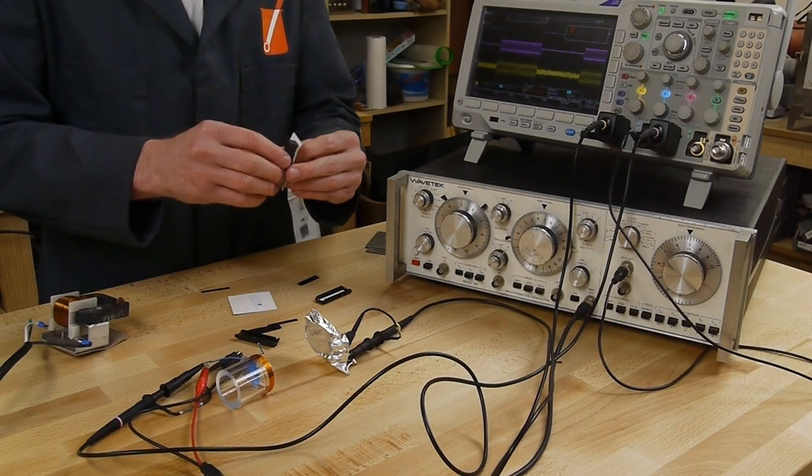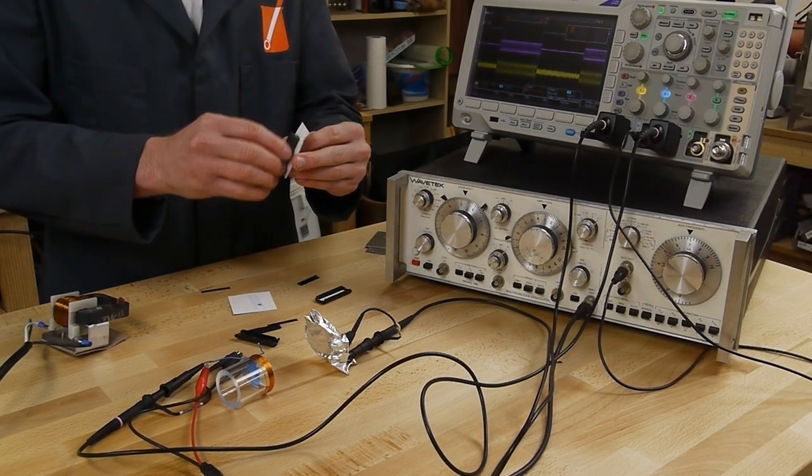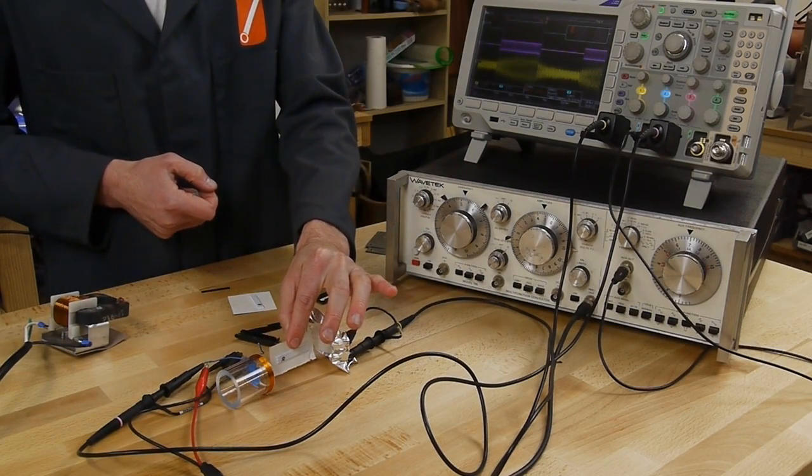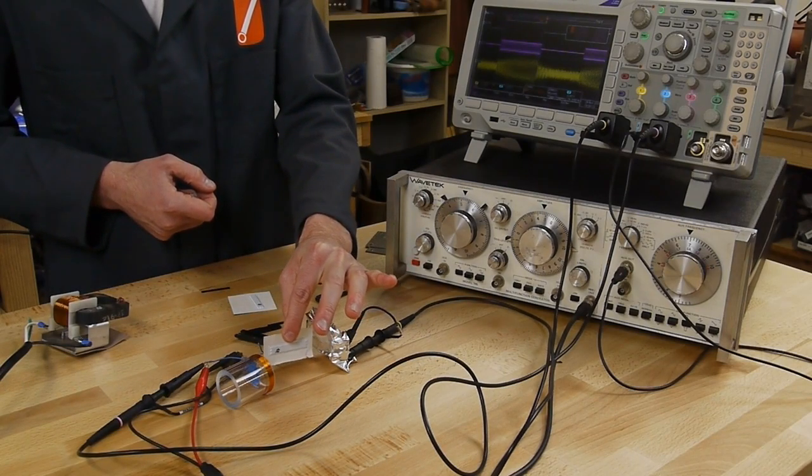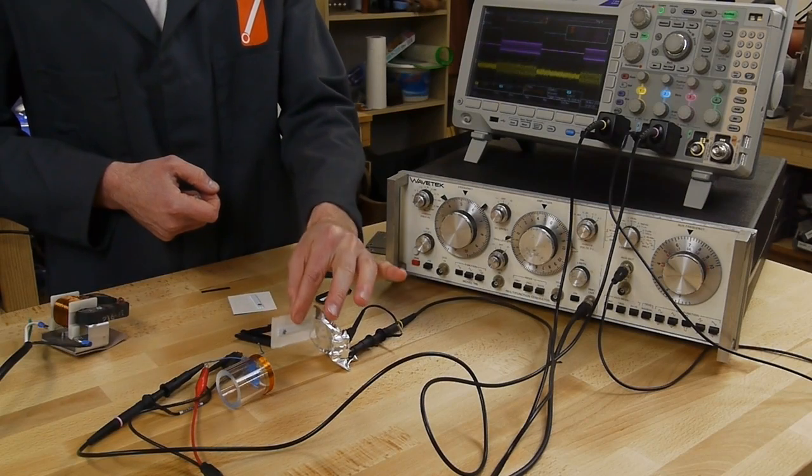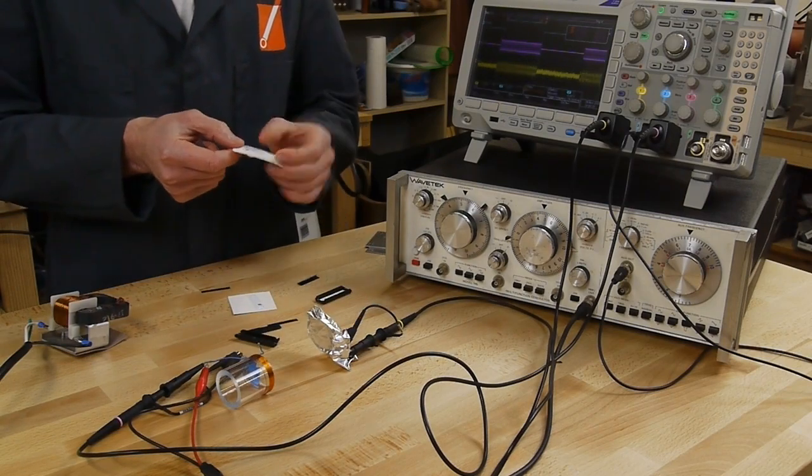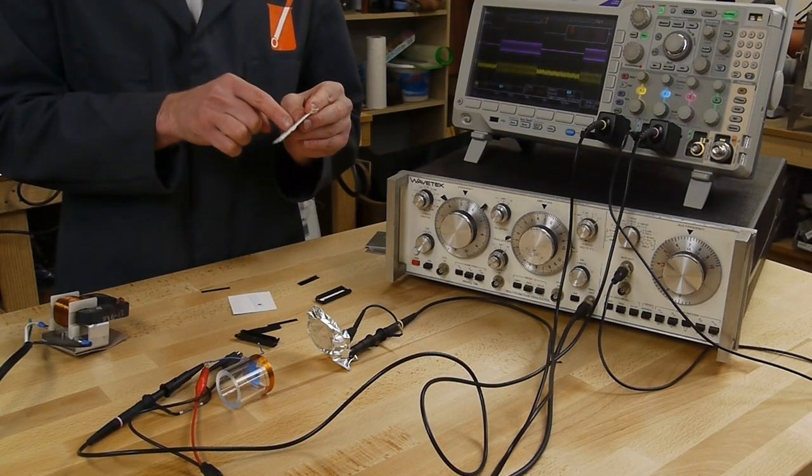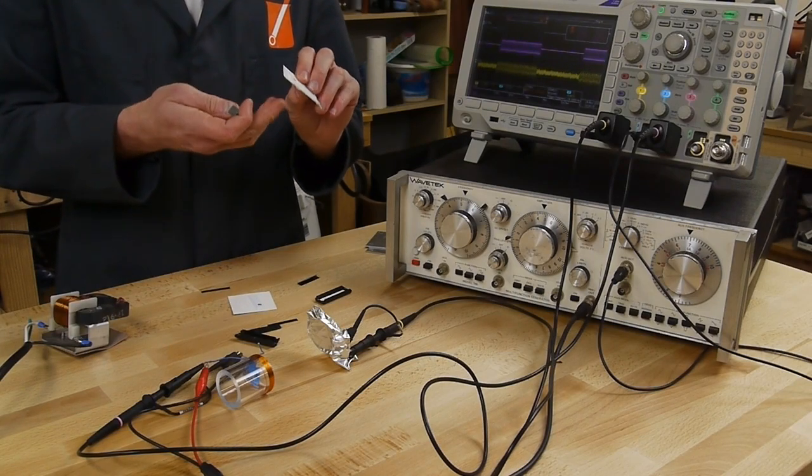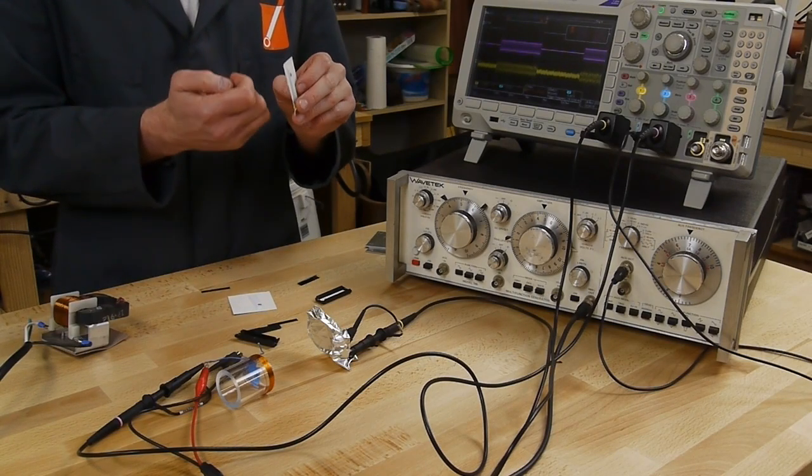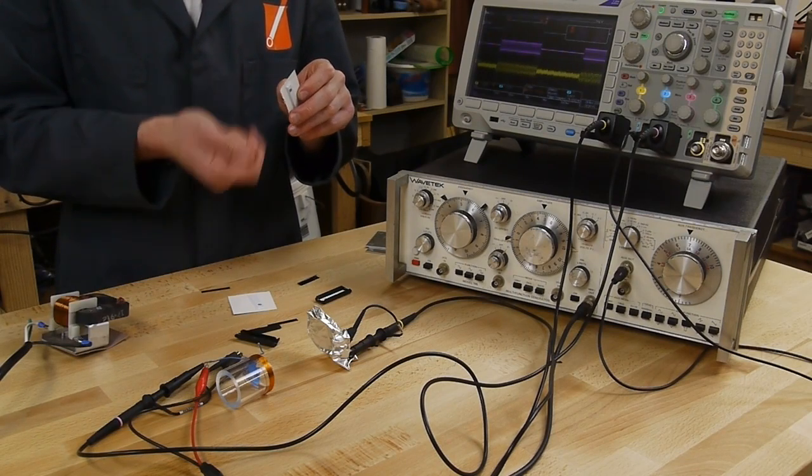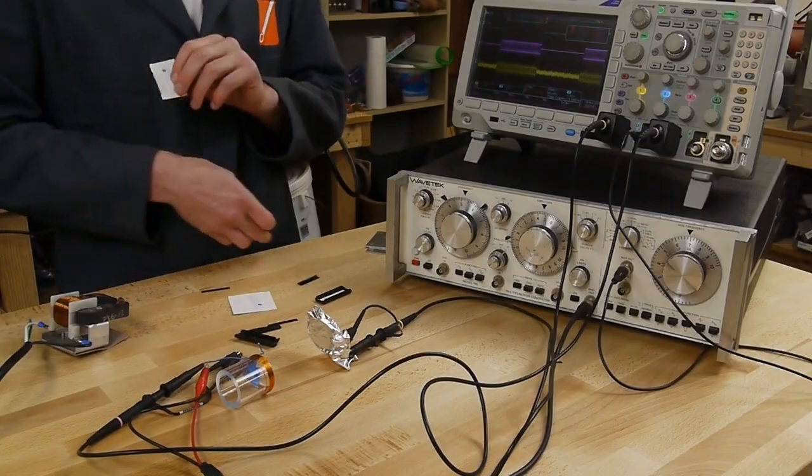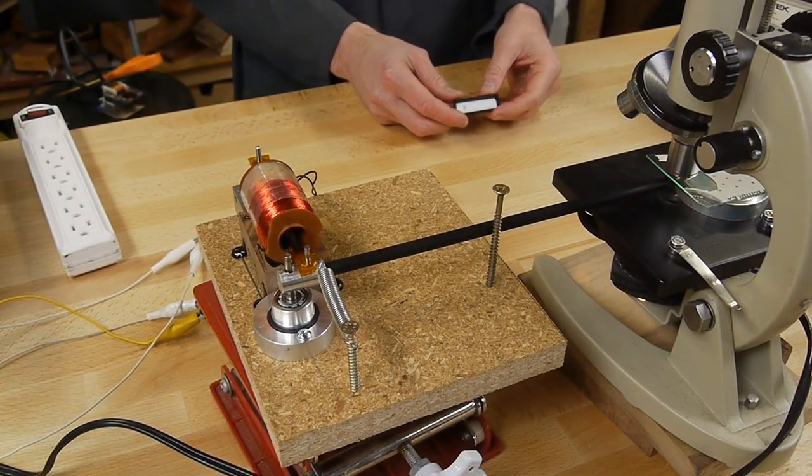Let's see if we can bring it back to life by putting this magnet near it. I'll put the magnet here and remagnetize the strip that's in there, hopefully, and we'll see if we're back in business. We are - it's not quite as much signal as we had when we started, but it's pretty close. You saw from the graph that the exact level of magnetization of the strip that's in here is actually important too. I came in here with a really big neodymium magnet and actually caused one of these not to work anymore because I over-magnetized it or something.